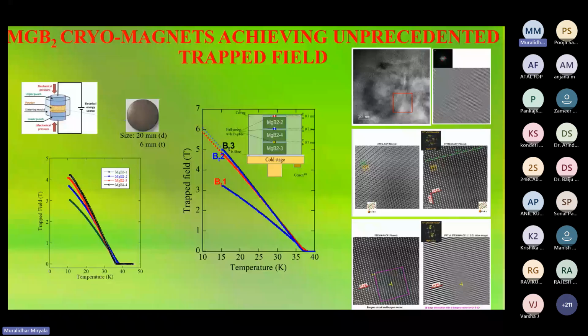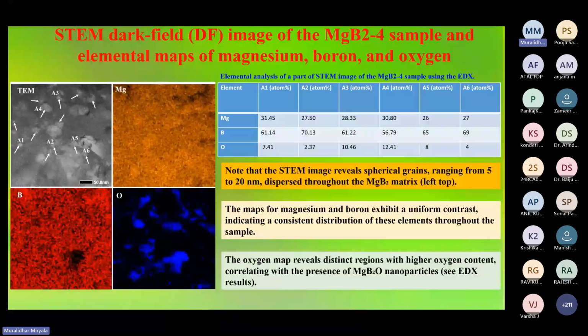Then what we found is that we controlled the nanostructural pinning inside the material. We also found a new class of nano pinning centers, which are MgB2O particles. You can see the elemental analysis in the top table: magnesium, boron, and oxygen.